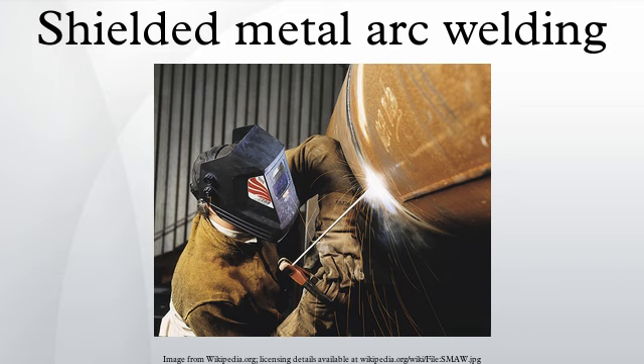It is caused by low current, contaminated joint surfaces, or the use of an improper electrode. Shallow penetration, another detriment to weld strength, can be addressed by decreasing welding speed, increasing the current or using a smaller electrode. Any of these weld strength-related defects can make the weld prone to cracking, but other factors are involved as well.